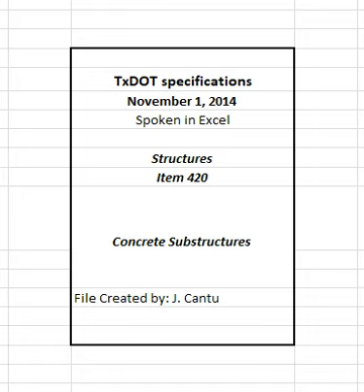4.1.2 Removal of forms and false work. Keep in place weight supporting forms and false work for bridge components and culvert slabs until the concrete has attained a compressive strength of 2,500 psi in accordance with section 420.4.11, removal of forms and false work. Keep all forms for mass placements in place for 4 days following concrete placement unless otherwise approved based on the outcome of the heat control plan outlined in section 420.4.7.14, mass placements.